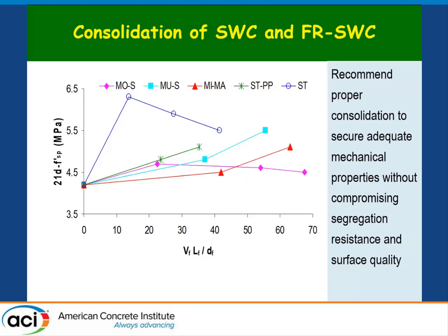But as Joe showed, when you have super workable concrete, where you don't have either very highly viscous concrete or not flowable enough, in this case, if you have a lot of fibers or high fiber lengths and you do not vibrate, you start having a reduction in strength. That is because you do not have self-consolidation. So for the mixtures here, whether they're synthetic fibers or metallic fibers, we've done splitting tensile, compressive, and flexural strengths, and they all point to the same trend. When you reach a certain loading of fibers, you don't have self-consolidation and you need to apply some consolidation.